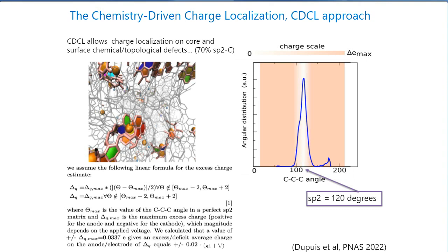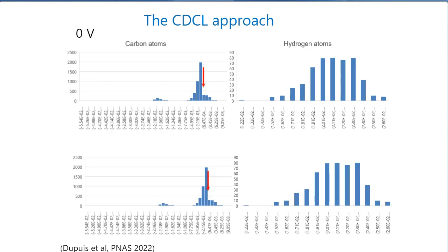With that CDCL technique, we run the simulation. First, looking at zero volts — the non-polarized electrodes — you see charges on the carbon and hydrogen atoms from our calculation. Both electrodes carry the same charges, and the red arrow indicates zero charge. Mostly the carbon atoms carry a negative charge, and the hydrogen and oxygen mostly a positive charge. Now moving to two volts: on the anode, everything is shifted positive, and for the cathode, everything is shifted towards more negative — that's the result of the polarization.